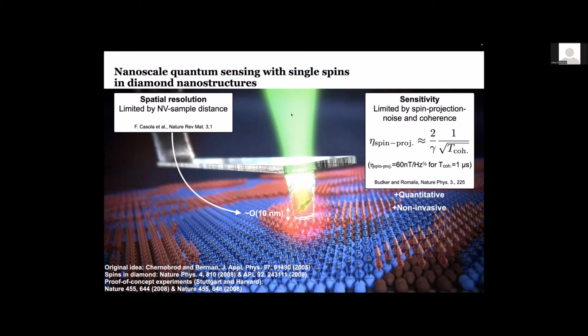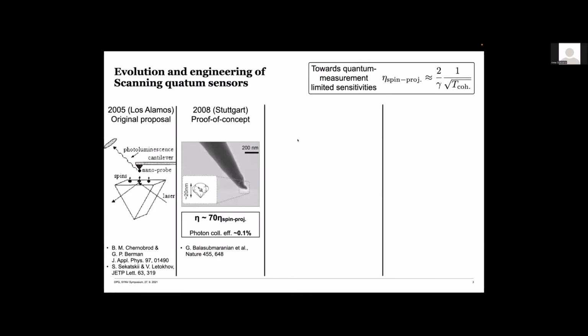And so I will just take one slide to show you a little bit where we stand in the field in our progress towards reaching this spin projection noise limit, and what type of engineering we're doing to improve the sensing performance of these scanning NV magnetometers. You've heard already in Vincent's talk quite nicely where this whole technique comes from, that this idea of scanning NV magnetometer really originated from this work by Chernobrod and Berman from 2005. And then the first implementation of this idea, in fact, comes from Stuttgart, where Rainer is working, and was first shown using essentially grafted nanodiamonds on scanning probes.